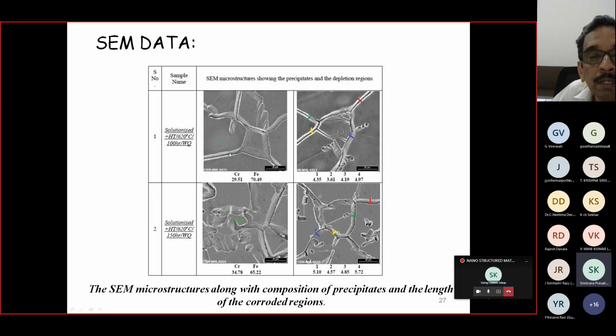If I see the composition, this is basically having iron and chromium. Nickel is also there, but it is not visible in here. That means the chromium concentration is increased. That is what I am interested in. Because if you remember, in the first slides when I showed the chemical composition of the stainless steel, it has 18 chromium. But now the chromium at this particular localized area has gone up to 20, 29, 34. So the chromium concentration is increased, and the iron concentration is remaining the same. So obviously the chromium has been pulled out from the matrix and has separated out. I'm sure that the chromium has come out, and that particular region is of the order of a few microns, 4 to 5 microns.